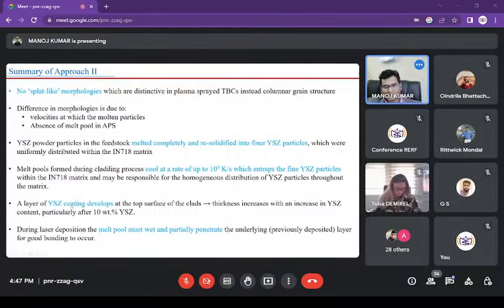And as I discussed, YSZ coating develops on the top of the clad zone. When we go for higher composition of YSZ, typically when we go more than 10% of YSZ deposition, we develop a thin layer of YSZ coating at the top of the cermet layer, and that we can see in two ways. One is that it poses a challenge for the next layer of deposition, but at the same time